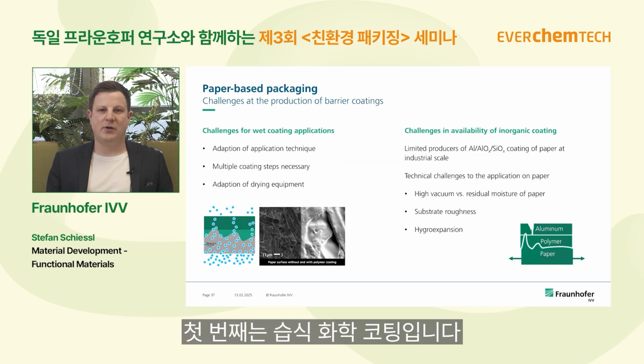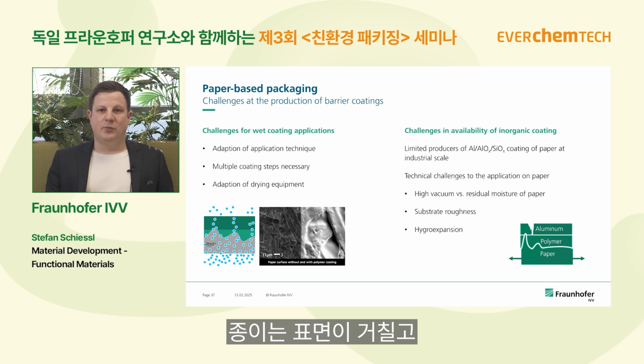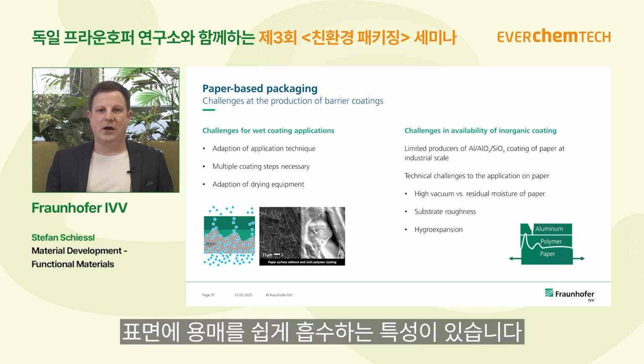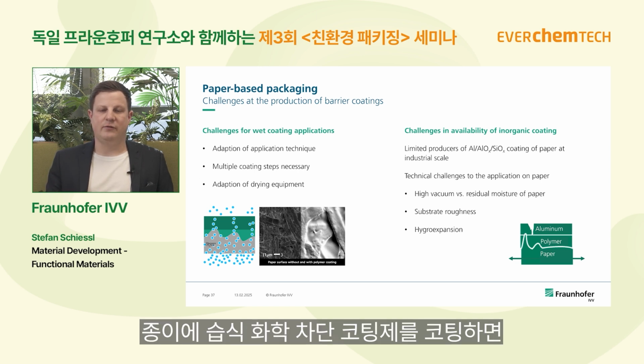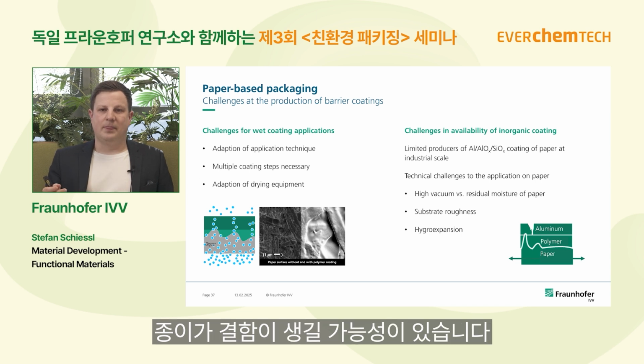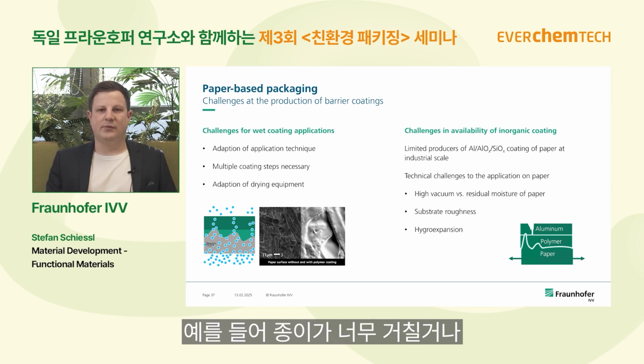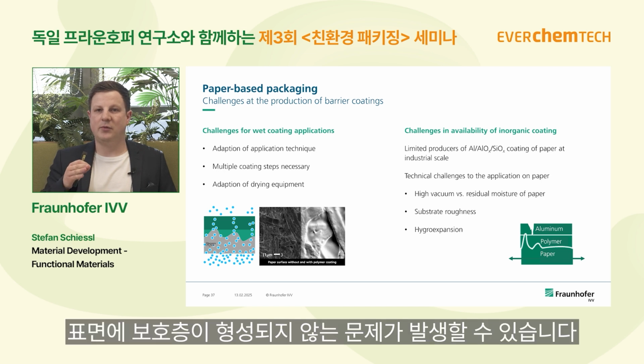Talking about the application of barriers on papers, we have two main challenges. First one, the wet chemical coating. As you might know, paper is very rough and has a very high potential to suck some solvents on the surface. So what is happening if you coat paper with a wet chemical barrier lacquer, then the paper is sucking some of the barrier lacquer, and this leads to the fact that we might have defects if the paper is too rough, for example, or that the whole lacquer is sucked by the paper and there is even no closed layer on the surface.